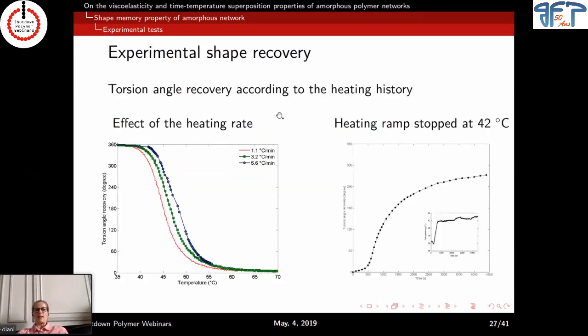So that gave us not only good recovery or bad recovery, but the kinetic of the recovery. And here you see the recovery according to the ramp of temperature heating from 1.1 to 3.2 to 5.6 degrees per minute. And you can see how the recovery is complete, but also you can see the kinetic and the impact of the temperature